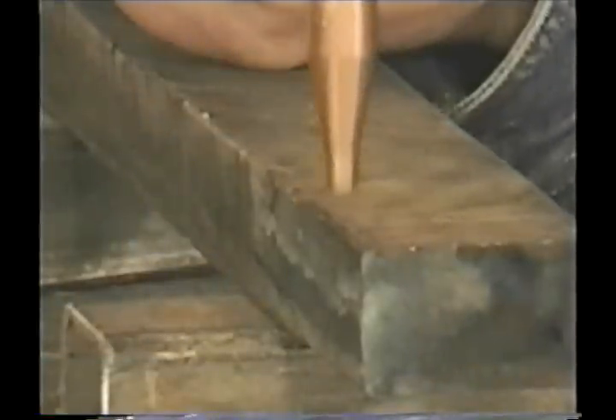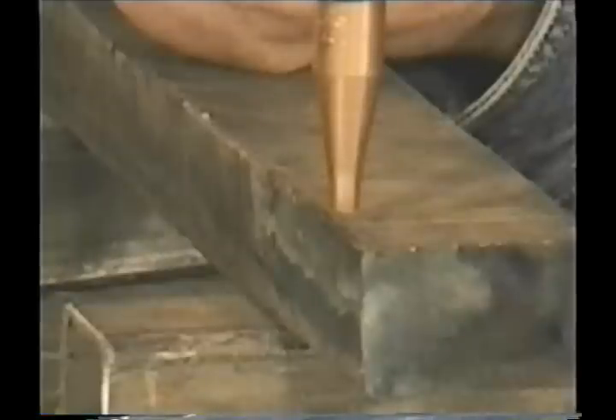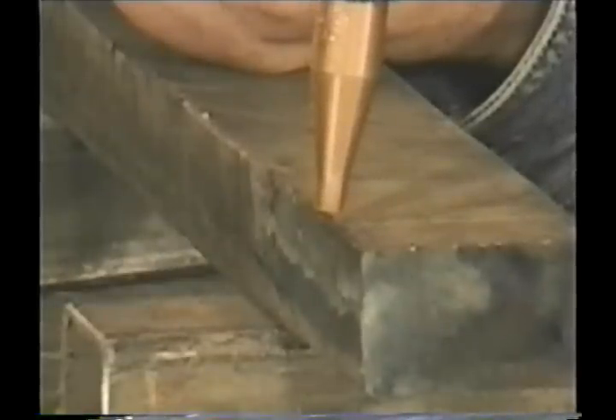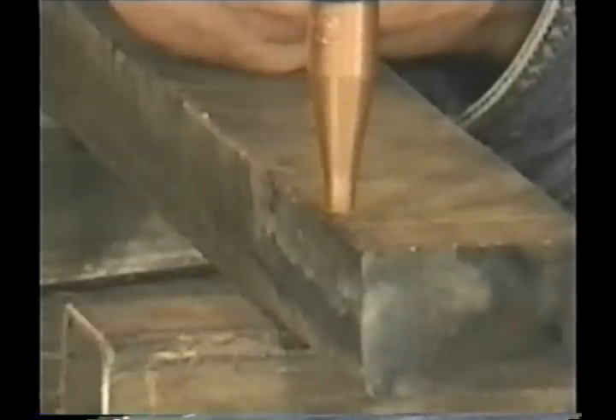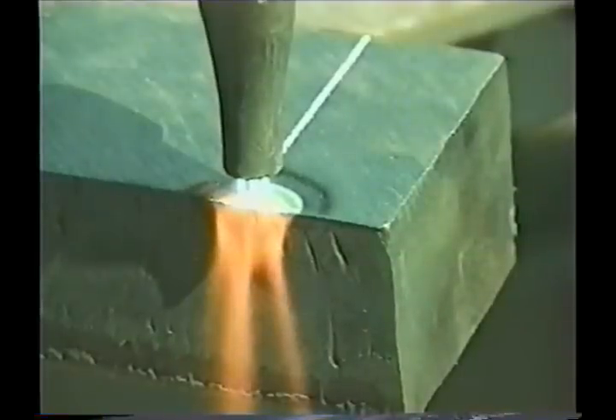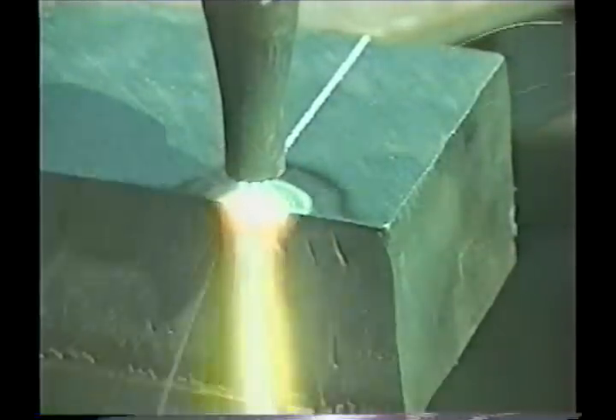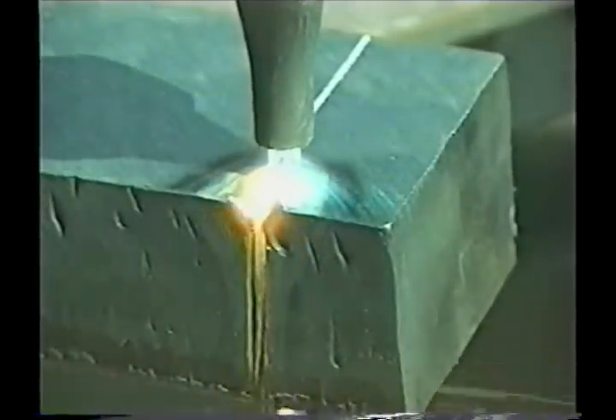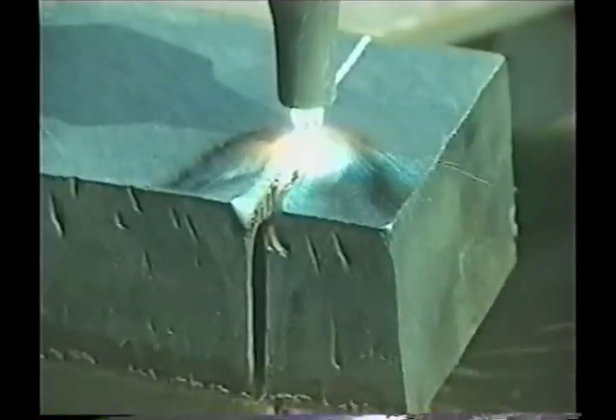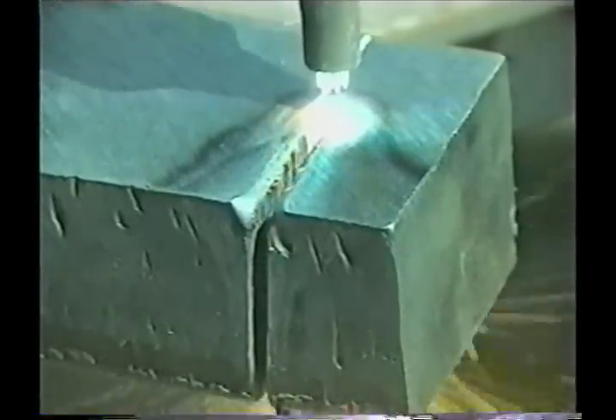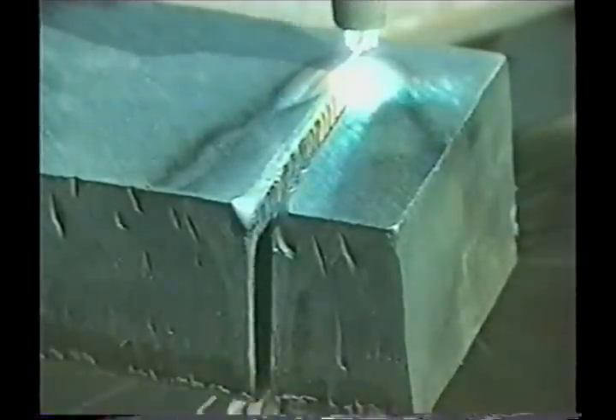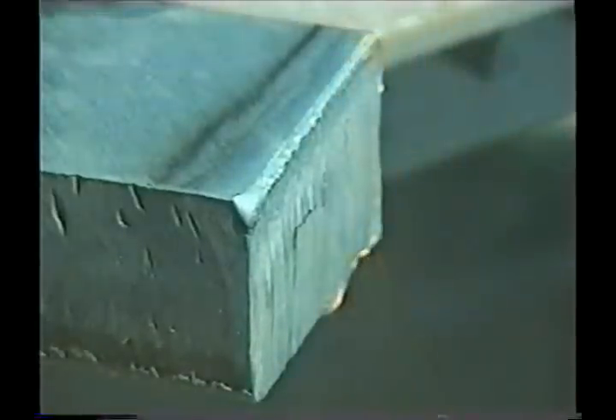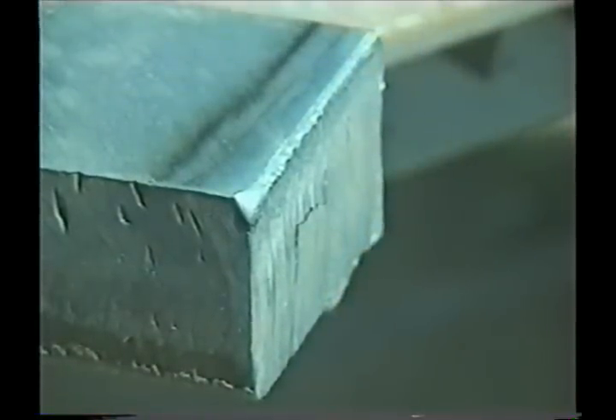You don't need to get the whole side red hot, just the top edge. Then rotate the tip back a little to catch the corner, push the cutting jet lever, rotate the tip straight up and down again, and start moving. This is 1¼ inch metal using a #1 tip with 5 pounds acetylene and 40 pounds oxygen. You want to go slow enough so the cutting jet has time to go all the way through. Too slow is better than too fast. You might have some slag stick to the metal, but that's a whole lot better than losing the cut. The thicker the metal, the more you need to take your time and be ready. You'll be a lot happier with yourself if you do it right the first time.